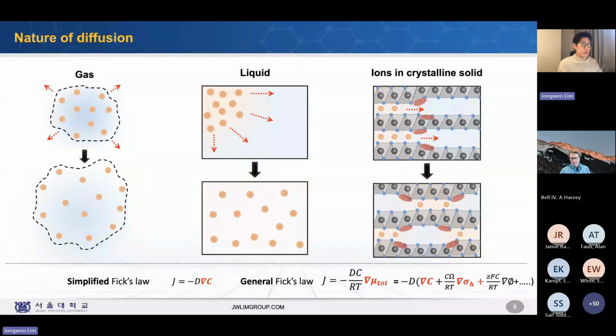And now, one of the questions here is that yes, the concentration gradient and also strain stress are very important. I'm trying to understand those phenomena. So in order to do so, we developed a technique called Picasso. It stands for primary particle in situ X-ray imaging with chemical composition analysis and stress strain observation.